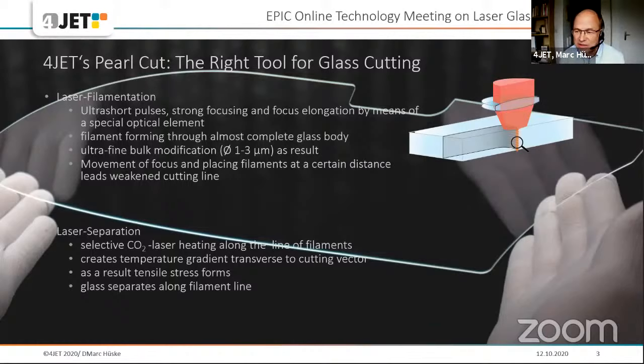And you can then use a stage, as has been said already, to move this filament line along the cutting edge. Now the glass is weakened and you can mechanically break it, or you can use a CO2 laser to automatically separate the glass by heating it along the lines of filaments. And this CO2 laser creates a temperature gradient transverse to the cutting vector, resulting in tensile stress, and then the glass separates automatically. This doesn't work for every type of glass. You need some value of coefficient of temperature expansion to make it work.